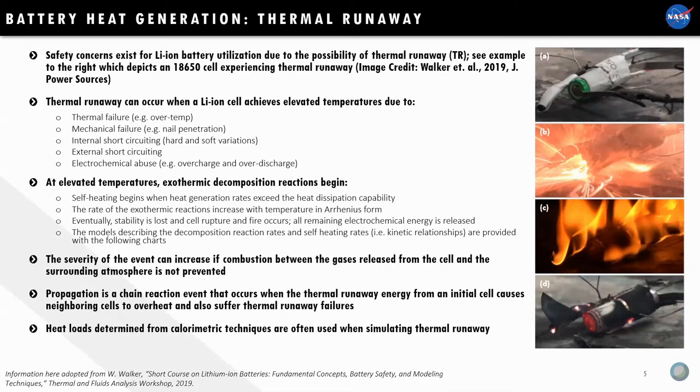So just a little bit of background about thermal runaway now. Thermal runaway is really a function of a cell achieving a high level of temperature due to several different items, which include thermal failure, like an overtemp; mechanical failure, like a nail penetration; internal and external short circuiting, of which we have hard and soft variants; and electrochemical abuse, like charge and discharge overcharging.